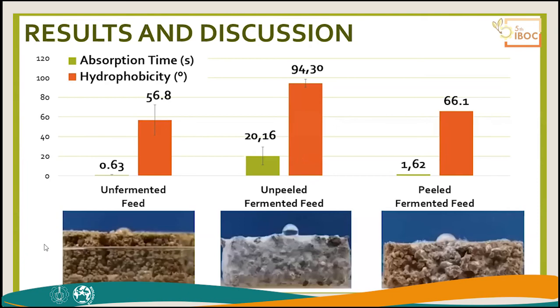Then we measured the hydrophobicity of the surface of these 3 feeds. As you can see, for the unfermented feed, when we tested using a droplet, the water droplet was quickly absorbed by the surface, and it took only 0.63 seconds to absorb the droplet completely. The contact angle is less than 90 degrees, so it means it is not hydrophobic; it is hydrophilic.